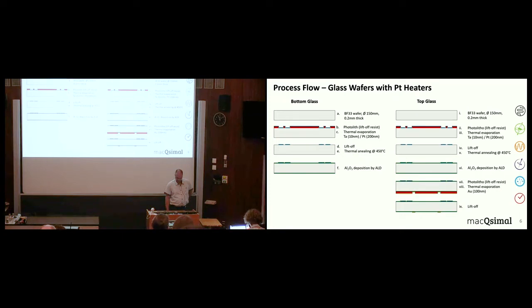For the top glasses, we have then some additional steps. We have again a photolithography on the back side of the glass here, and then we make a thermal evaporation of gold. So here we fabricate gold discs, and I will come to this topic just afterwards. We remove the photoresist with all the residual metal on it, and we end up with a wafer having here the platinum resistive heaters and here gold discs on the other side of the glass.